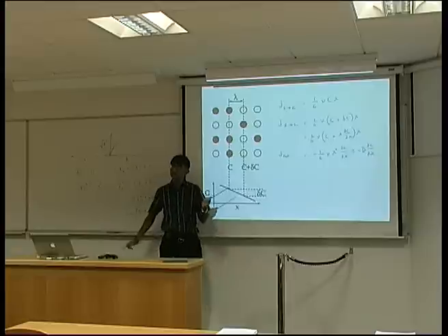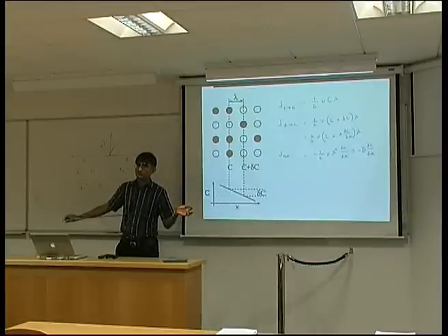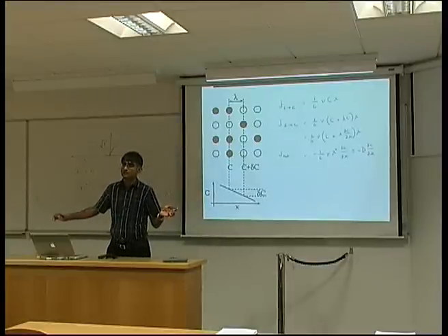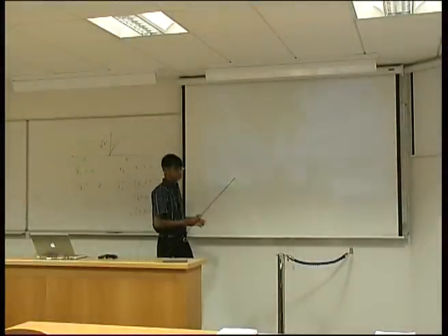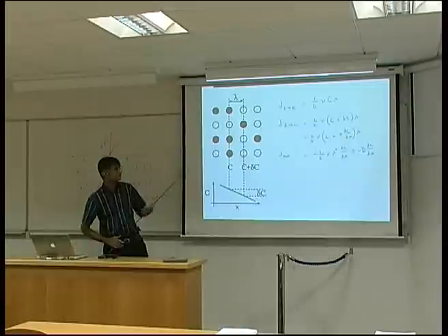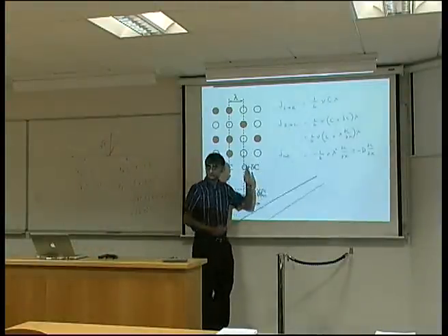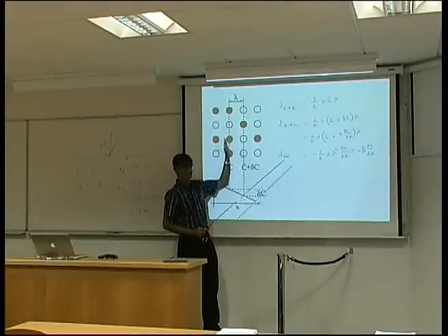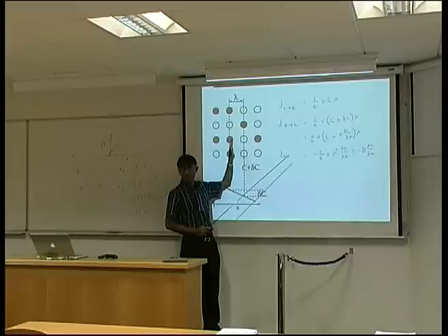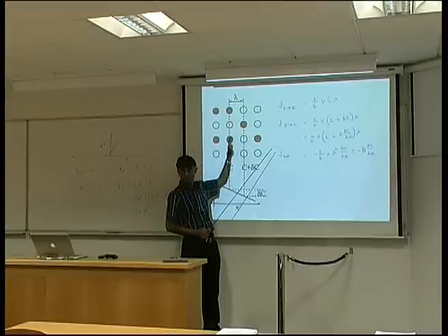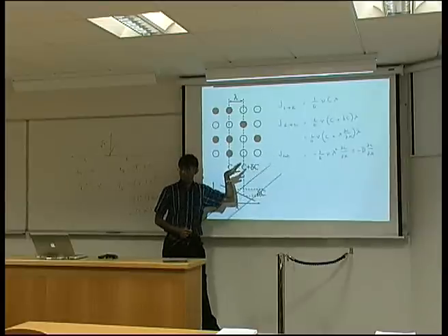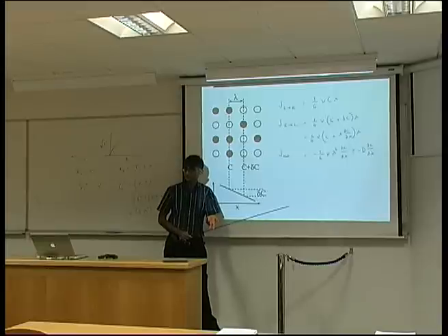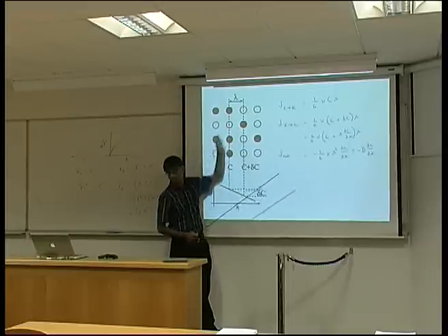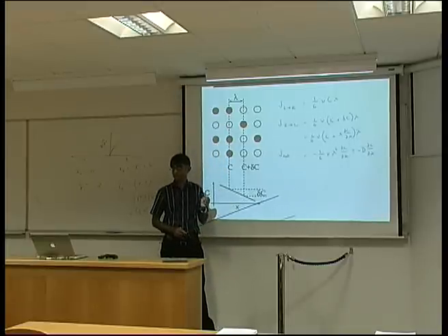I couldn't get the point why lambda has been considered as an area unit and not length. As a volume. It is actually a length. Okay, but we are considering one unit area. Lambda is in this direction, and we are considering one unit area. So if I multiply lambda by 1, that gives me the volume of this plane, the unit area of this plane. And then I multiply by concentration, which is atoms per unit volume. So I get the number of solute atoms in a unit area of this plane. Okay?